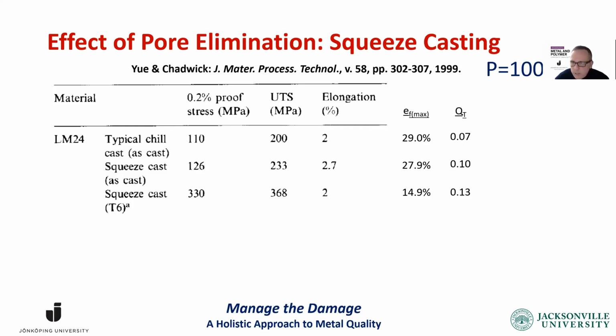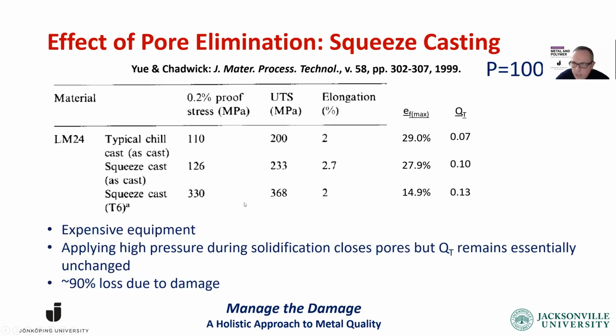And then when we heat treat it, there is some beneficial effect of solution treatment in healing the oxides, but very little. You gain another 3%. So what do we learn from this? Yeah, we have a lot of expensive equipment applying the pressure. Basically, the quality index remains unchanged, and we still lose about 90% of available ductility to damage. And that has tremendous implications for the performance of the casting, especially fatigue performance. And that may be another webinar in the future.